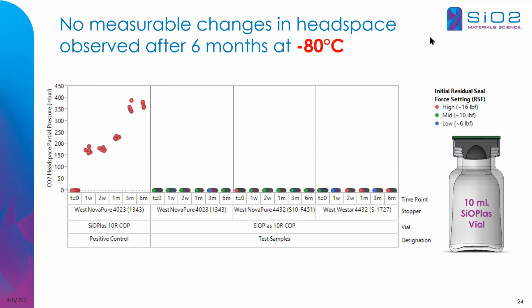What we're showing here on the left is the positive control, with the 5-micron hole in the container, showing how the concentration of CO2 changes in the container over time. And then the test samples, which are using different types of stoppers. What you can see here is very good container closure integrity maintained at -80 degrees C.